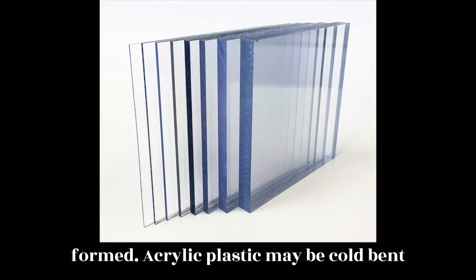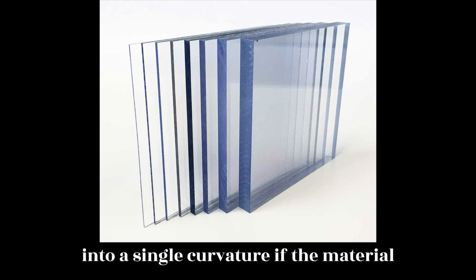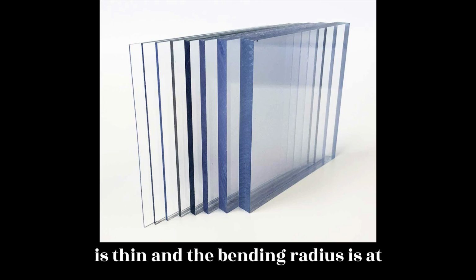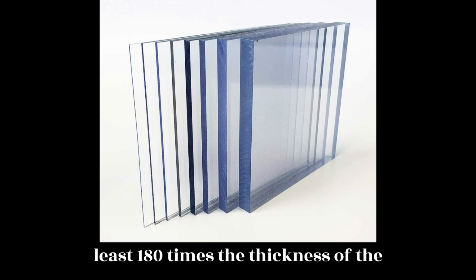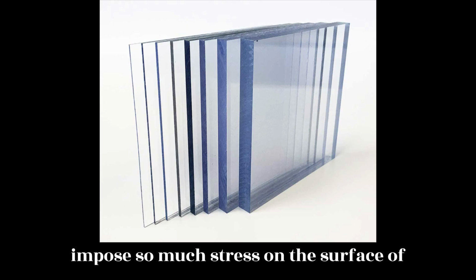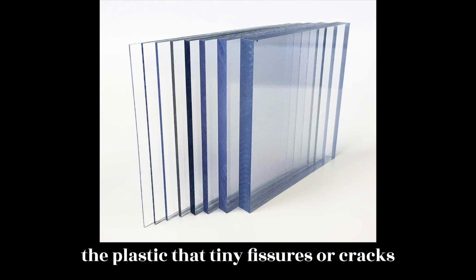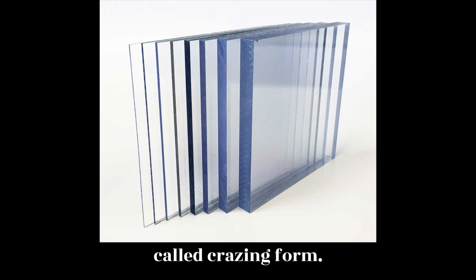Acrylic plastic may be cold bent into a single curvature if the material is thin and the bending radius is at least 180 times the thickness of the sheet. Cold bending beyond these limits imposes so much stress on the surface of the plastic that tiny fissures or cracks, called crazing, form.